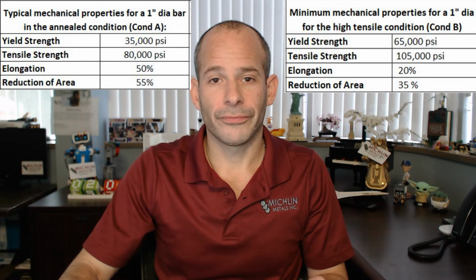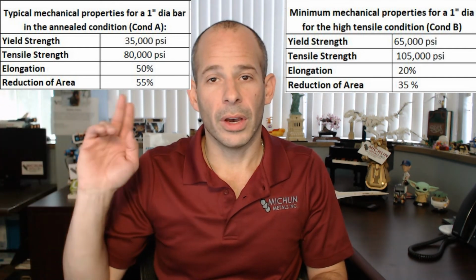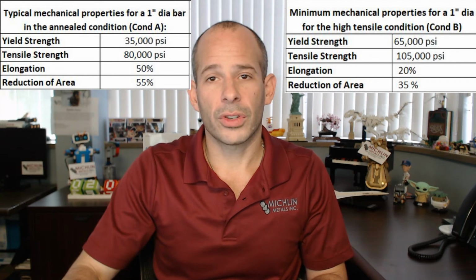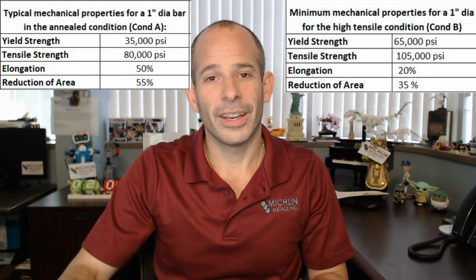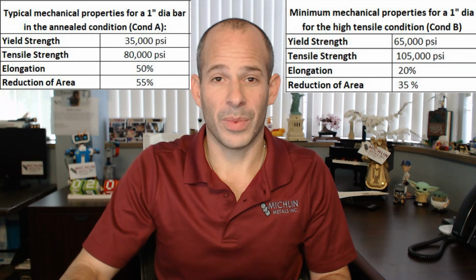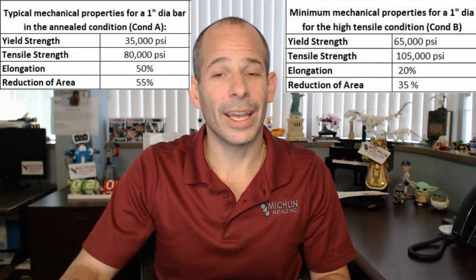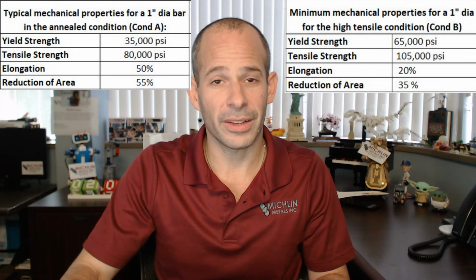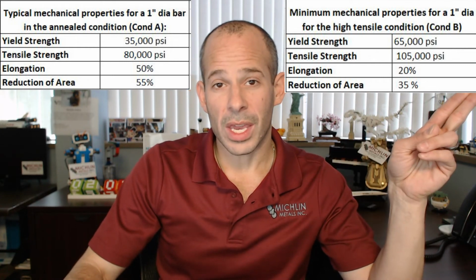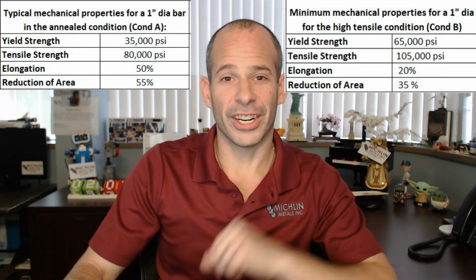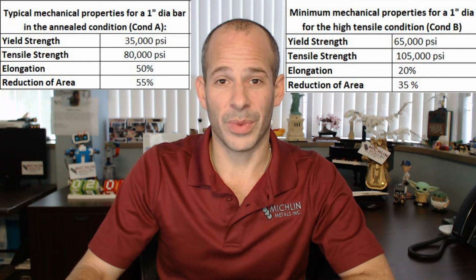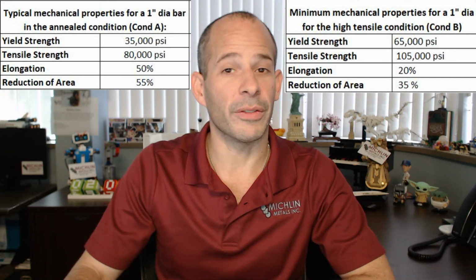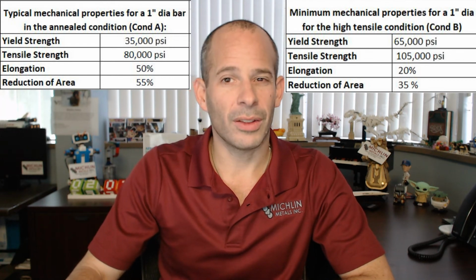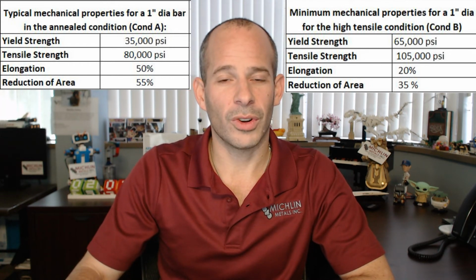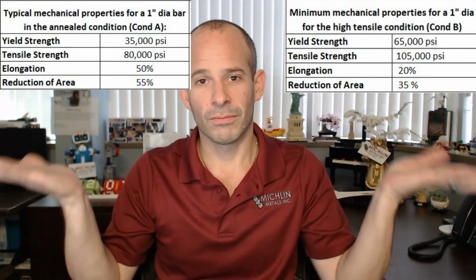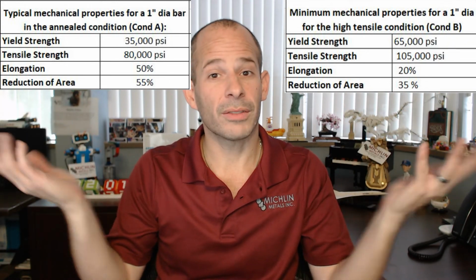And so what do we got? On the annealed properties, we have a yield strength of 35,000 psi, a tensile strength of 80,000 psi, an elongation of 50%, and a reduction of area of 55%. And for condition B, the mechanical properties for the 1 inch are a yield strength of 65,000 psi and a tensile strength of 105,000 psi with a 20% elongation and a 35% reduction of area. Compare, contrast, do what you will.